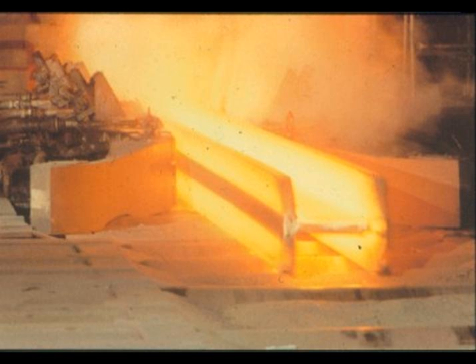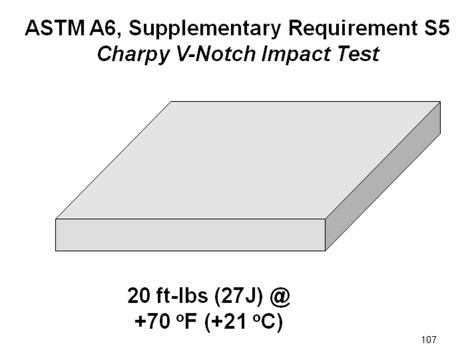Now, that caused the steel producers to have to produce the steel differently in order to get the properties out of that location. And here is a new shot of the steel being made where they're artificially cooling that web-to-flange interface to ensure appropriate properties at that location. Now, the Northridge problem started out as shapes, but eventually the same provisions were applied to plate. And when the plate exceeded 2 inches, when you had a tension splice, we had the same requirement of 20 foot-pounds at 70 degrees. There needed not be a different location for that because that zone would be passed all the way through the plate.